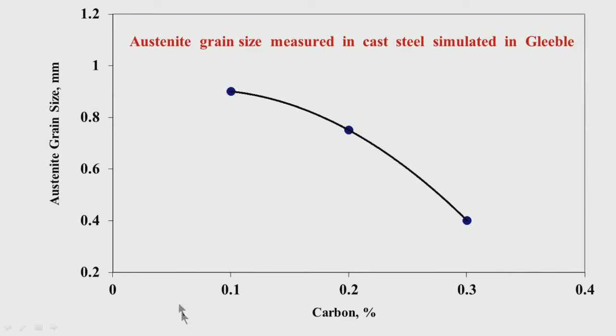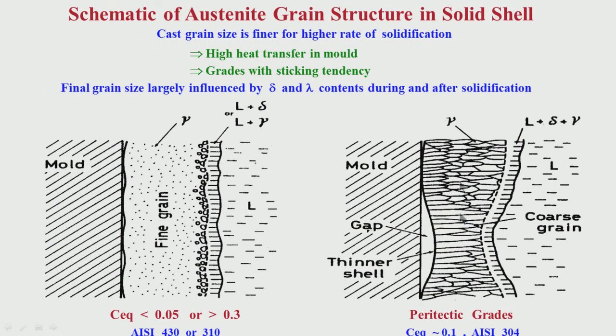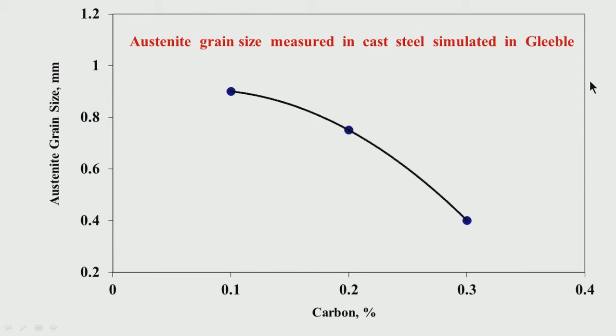So, we have found that 0.1% carbon, as I had told you, the so called peritectic chemistry, has a relatively larger grain size, around say 0.9 millimeter, which is quite big. And when we come to say 0.3% carbon, you see it is relatively less, 0.4, so it is more than double. So, at 0.1% carbon, the peritectic composition, the cast grain sizes of austenite are relatively larger. You can see here actual measurements done during solidification, which has been simulated in a Gleeble machine. So, the austenite grain size is quite large, around 0.9, quite large.